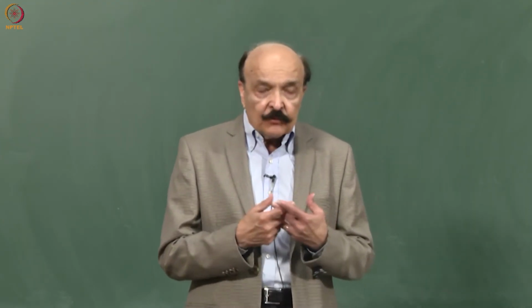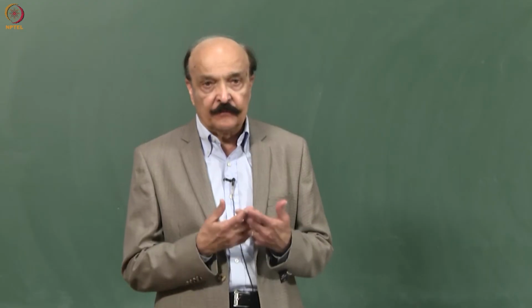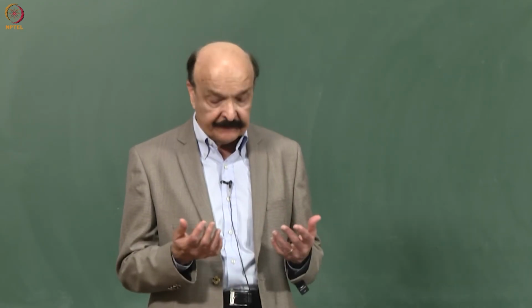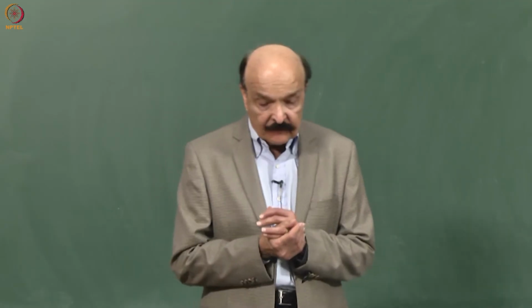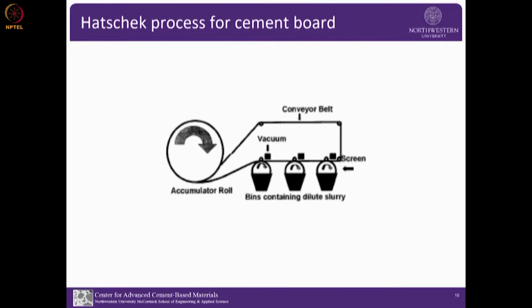So people are looking at alternate methods of production than cast in place. One of them is this so-called Hatschek process, which was developed in Austria, and it's widely used for so-called cement board. Cement board is, you have a very dilute slurry originally with asbestos fiber, and then layer by layer it's deposited. So this is in fact the first example of so-called additive manufacturing, because you have layer by layer manufacturing and you get cement board.